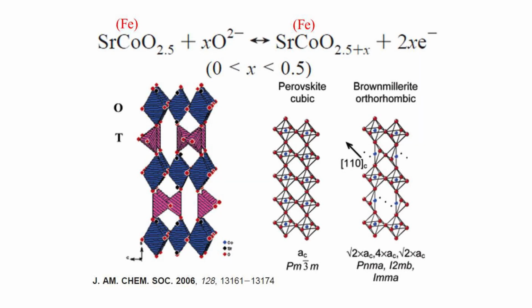So these materials in the oxygen 2.5 state have a brownmillerite structure. This means that in a simple way, the system is much more complex, but we can imagine that we have an alternation of blue and red layers. The blue layers are octahedral sites for cobalt or for iron, and the red ones are tetrahedral, okay? And when we are adding oxygen, we change the stoichiometry, and at the end we have a cubic perovskite, which is a much simpler structure.